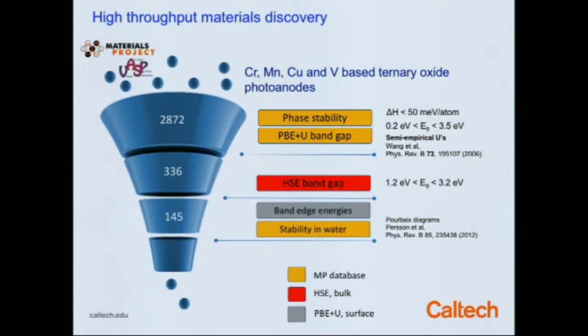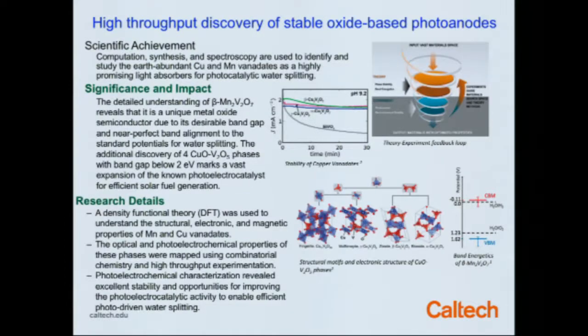And from those, we were able to screen down to a few hundred candidates. Then we used the hybrid functional method to make more accurate band gap calculations, much more accurate for oxide materials and mixed valence materials, to derive the band edge. And then finally, we tested experimentally a number of these materials, looking at their stability in water and their band edge energies. So this illustrates the process.